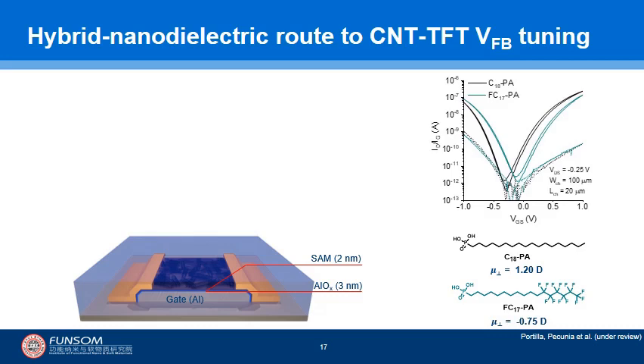In order to achieve the desired flatband voltage shift, we considered using a hybrid nanodielectric comprising a SAM molecule with dipole moment opposite to the molecule we considered earlier, as shown here. In fact, this led to a rigid shift in the transistor characteristics by an amount in the 0.1 volt range, as shown in this plot.